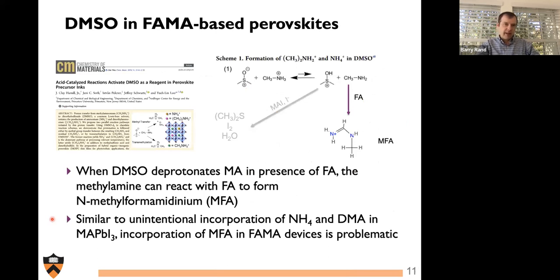Further on, what Clay did was to recognize that when we have the deprotonation of methylammonium through proton transfer with DMSO, the presence of methylamine, the deprotonated methylammonium, when in the same ink as formamidinium, will lead to a reaction between formamidinium and methylamine, or as generalized later, and we'll show, leads to the formation of this N-methyl formamidinium cation.